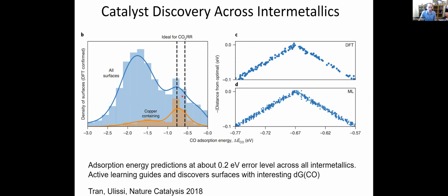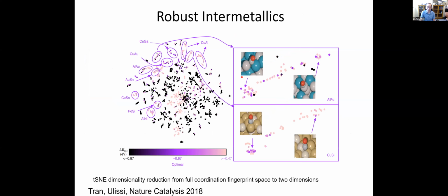There were more things than we could actually verify with DFT. And what we did was we were talking to experimental collaborators at the University of Toronto, and we said, look, we have all these materials that we think are interesting, various compositions, and quite a few of them we've done DFT calculations, and they should have a really interesting CO and hydrogen binding energy. So why don't we go ahead and test some of these things experimentally?